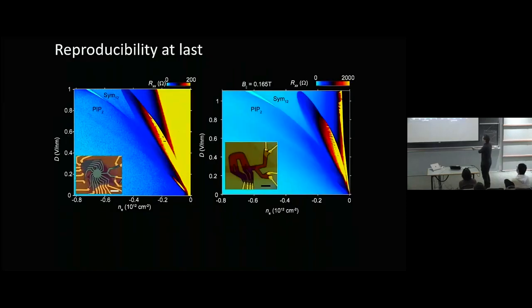Okay, but I think an important thing for us has been, at the experimental level, that these are just very reproducible. These are two different samples, right? And if you look, both of them start superconducting just shy of 1 volt per nanometer. They start superconducting exactly the same way. They're essentially quantitatively identical. TC is the same, 30 millikelvin, 30 millikelvin, it's all extremely consistent. So this means that we can now do experiments and actually have controls, which is actually useful.